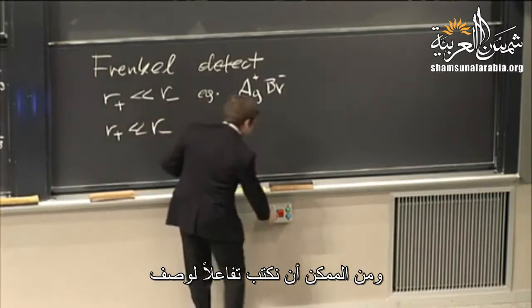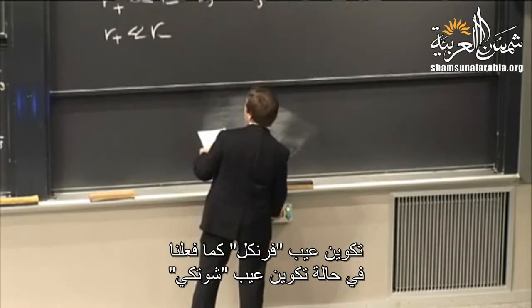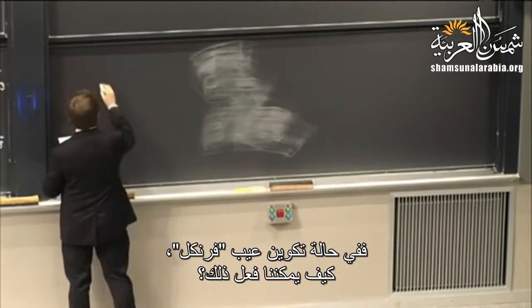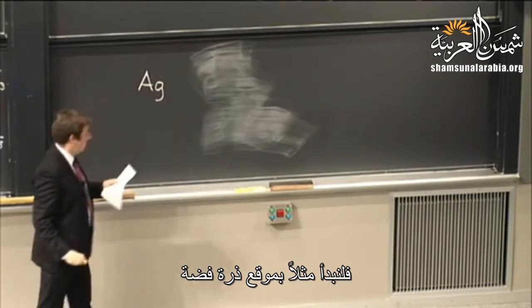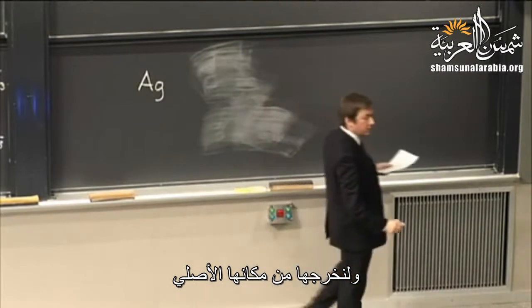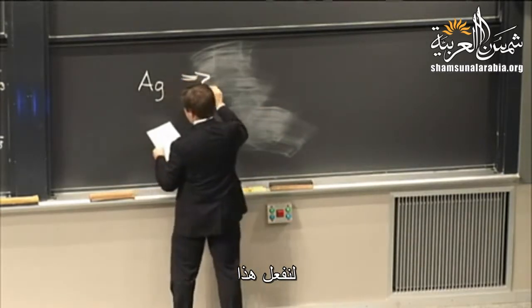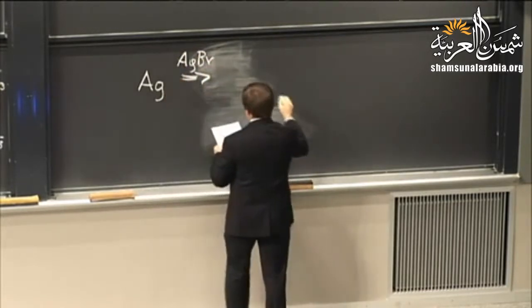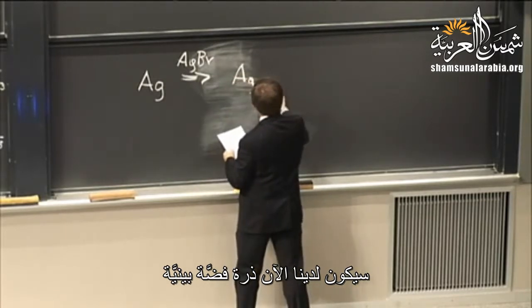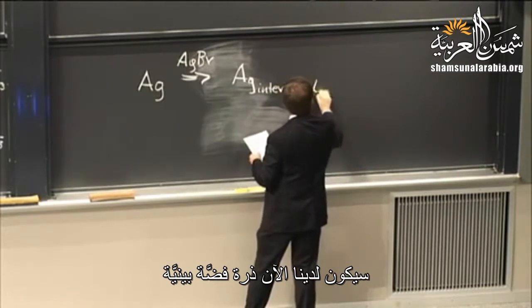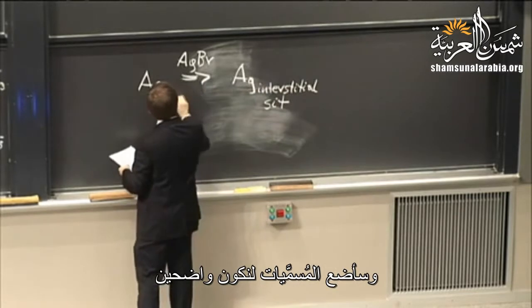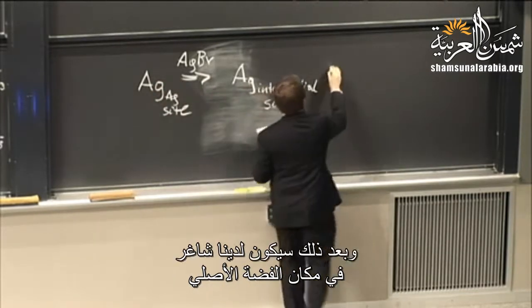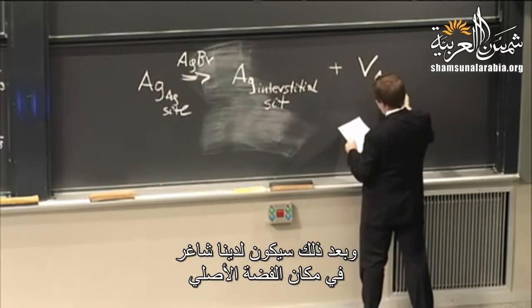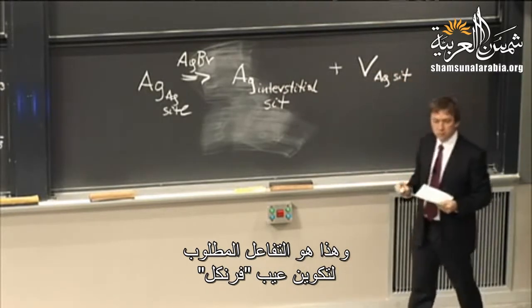And we can write down a reaction to describe the Frenkel defect formation, just like we did in the case of the Schottky defect formation. So in the case of a Frenkel defect formation, how do we actually go about this? We can start out with a silver atom site, and we're going to displace that silver atom away from its original site so that it now sits in an interstitial position, and we're going to leave behind a vacancy. So let's do that. We're going to have a silver interstitial site. And let's just, to be clear, say that this is on a regular silver site. And then we have a vacancy left over on the silver site. And this is the reaction for the formation of our Frenkel defect.